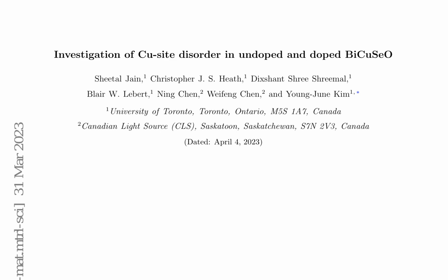The Cu K-edge EXAFS results confirm the presence of significant disorder at the Cu-site in both undoped and doped BiCuSeO, primarily along the Cu-Se atom pair. The introduction of Ag at Cu-sites in the doped samples does not affect the disorder of Cu atoms, as the values of sigma squared are nearly identical for all dopings at all temperatures. The overall mean square displacement for Cu from EXAFS, sum of sigma squared, and XRD, UISO, are found to match within error bars, suggesting that contributions from further shells of neighboring atoms are not significant compared to the first shell, Cu-Se.